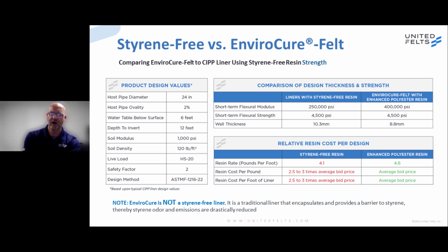With the styrene-free, this product is typically 2.5 to 3 times more expensive than what you see with enhanced resins. Therefore, your resin cost per linear foot is 2 to 3 times the bid price of what most owners are accustomed to. And imagine if you have a $1 million budget for infrastructure lining. By requiring a styrene-free resin, you're cutting the total footage that you're going to be able to line within that budget significantly, especially when the styrene-free resin, if you are requiring that, is 2 to 3 times the cost of traditional enhanced polyester resins.